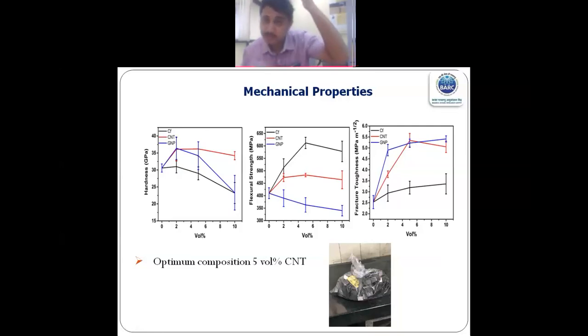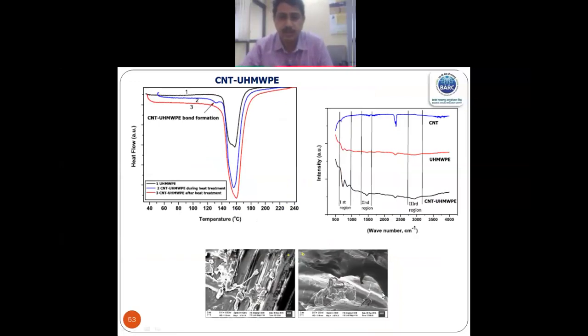As we already had the capability of making carbon nanotube in large quantity, we have utilized them for making the composite. Here you can see that tiles are made, and with those tiles we make the HAP, that will show how we make it. Also we use CNT with ultra high molecular polyethylene as backing. Here you can see the DSC image where it shows there is a bond formation with carbon nanotube, where it is pressed at a temperature and pressure along with the ultra high molecular polyethylene. With that bond formation, it makes that particular polymer very stiff, and the elongation to failure, that is strain to failure, also improves. So finally, this gives you a low backface signature.